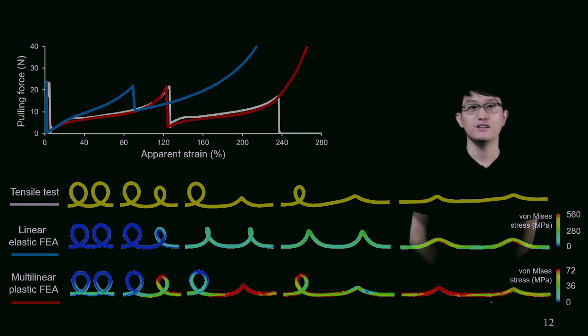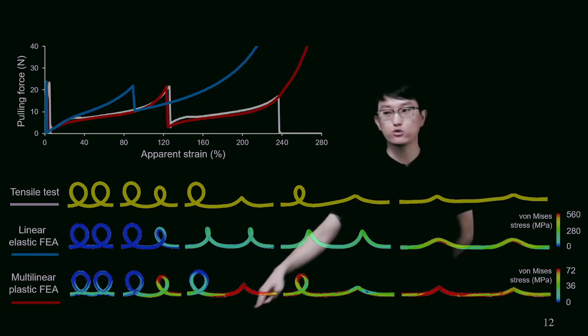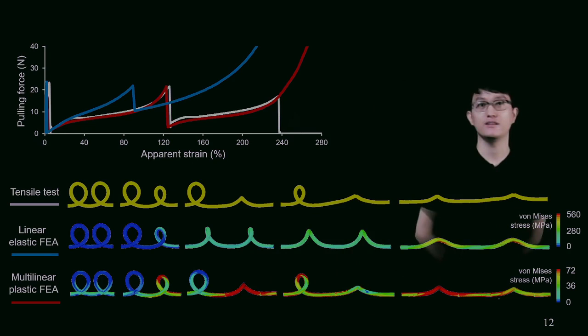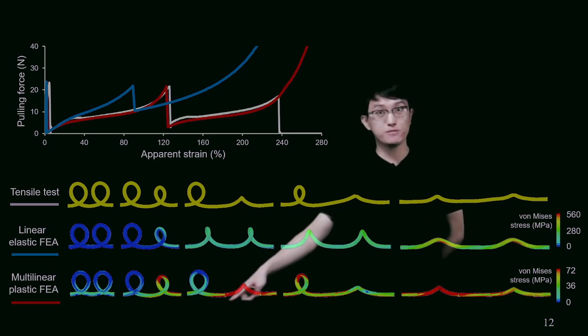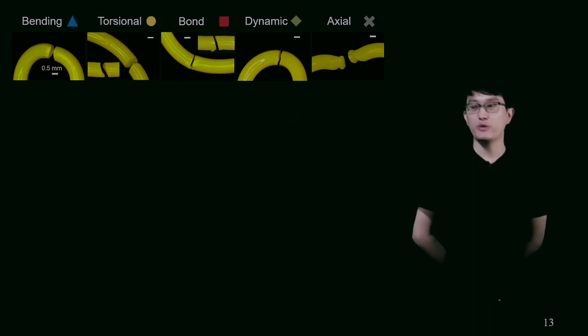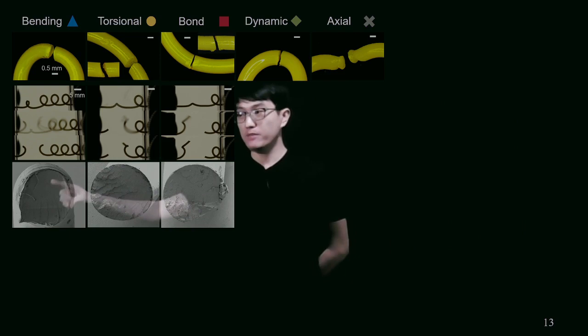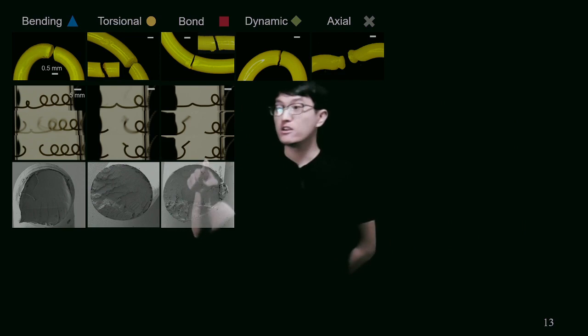The multilinear plastic FEA shows better agreement with the tensile test in terms of both the tensile curve and the unfolding geometry. This underscores the importance of plastic deformation during the fiber loop unfolding process — the material must be able to undergo large-scale plastic deformation before a new sacrificial bond can be broken. If the material is not ductile enough, the fiber backbone will break prematurely. The PLA polymer we initially used has a pretty low ductility, around 5% strain, which leads to multiple failure modes observed in tensile tests. The first three failure modes are static failures with brittle fracture, and SEM images of the fracture surface show that crack initiation regions of these three failure modes correspond well to the high tensile stress regions in the simulation.